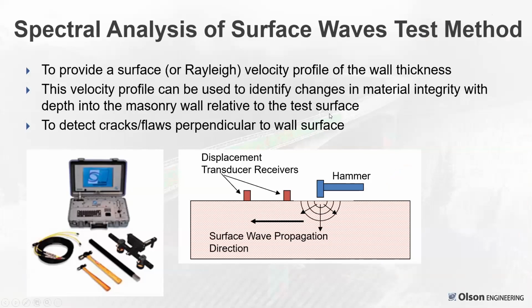The second test we did was spectral analysis of surface waves. Both of these tests are discussed in the ACI 228 document, as well as the ASTM standard for impact echo. But basically, this is the equipment shown on the left of the bar, where you can go from close spacings with an extension bar from like 6 centimeters out to 80 centimeters by moving these transducers, and further apart sees deeper. At least in a simple sense, without serious flaws, you'll see at least twice the spacing of the receivers, sometimes out to 3 times.